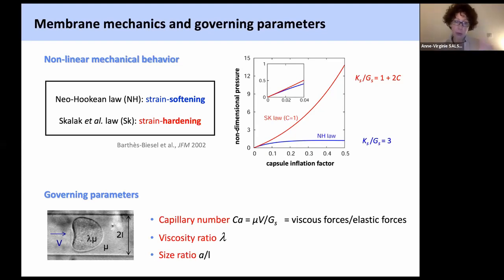In the experiment that I will show you, we'll do the reverse, because we'll take a microcapsule with a water solution inside, and outside we will put glycerol. Glycerol has a very high viscosity. It has a viscosity 1,000 times that of water. And thanks to this very high viscosity, we'll have high shear forces, so very high deformation.